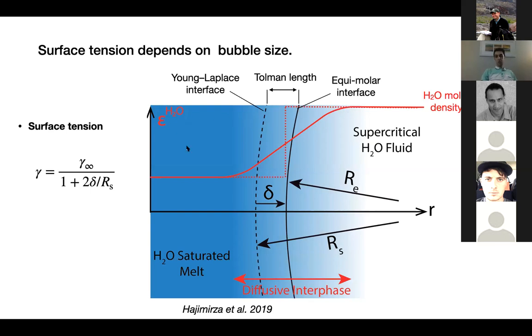This is a cartoon showing the theory of interfaces by Gibbs, suggesting the interface between two different phases, here melt and bubbles, is not sharp, but rather diffuse, meaning water molar density just gradually increases as we go from melt to the bubble.